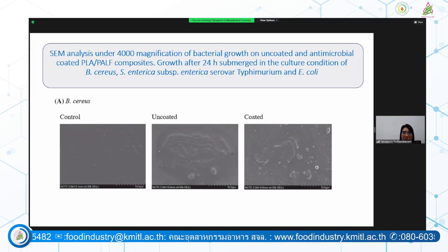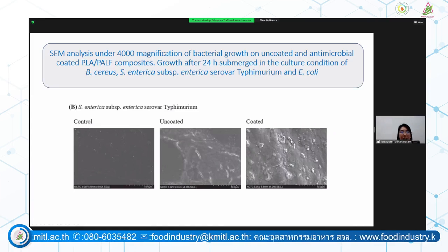From the test after 24 hours, we take the coupon out from the flask, and then we dry it in the freeze dryer and look at how bacteria attach to the material under the scanning electron microscope with 4000 magnification. We also test with the three indicated foodborne pathogens. This is from Bacillus cereus. The control, uncoated and coated control, we don't add any microbe in there. The uncoated is the material PLA, PALF without the active compound. This is coated with the active compound. So you see the number of cells is reduced on the material itself. It doesn't attach much to the material.